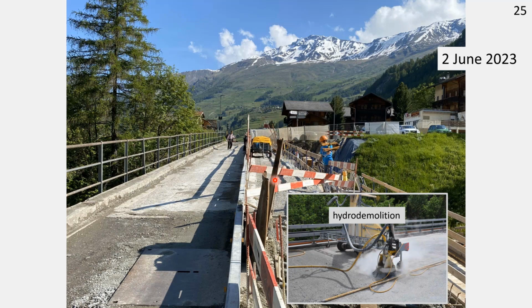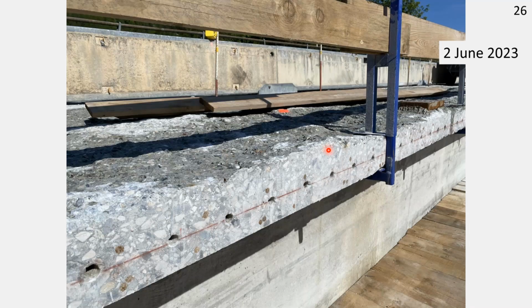And on the right hand side, the works are ongoing, and the curbs were actually cut, and the top layer of the existing concrete was removed by hydro demolition, about 1 inch was removed. And here we have a look at the cut surface when the curbs were removed. And also on top here, you see the surface after hydro demolition. We inserted here rebars more for constructive purposes in order to have reinforced the link with the new cantilever slab also on the compression side.